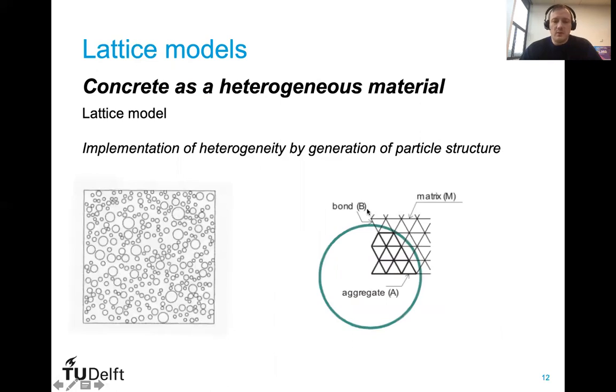How do we do that? We simply overlay our lattice on top of a material structure and assign different properties to different beams. If both beam ends are within an aggregate particle, we assign it the material properties of an aggregate. If both beams are within the matrix, we assign them the matrix properties. And the mixed beams have properties of the bond. This way we can assign different mechanical properties to different parts of our model.